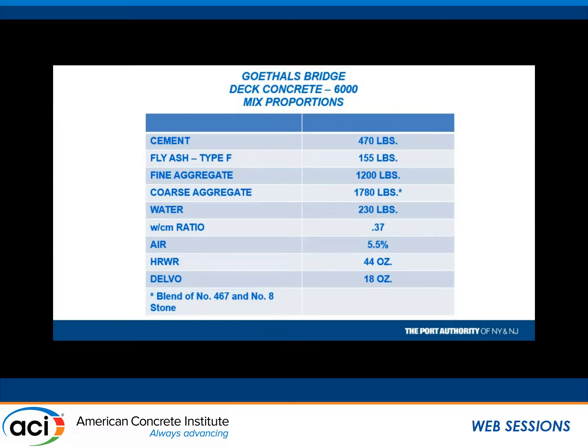So anyway, here's the mix design. Type F fly ash, 25%. We wanted 30%, so we had to give the contractor something. For whatever reason, they wanted 25%. We said our experience is 30% works the best. They wanted 25. We said, okay, go to it. Water cement ratio 0.37, air content, and Delvo. We wound up putting in 18 ounces of Delvo.